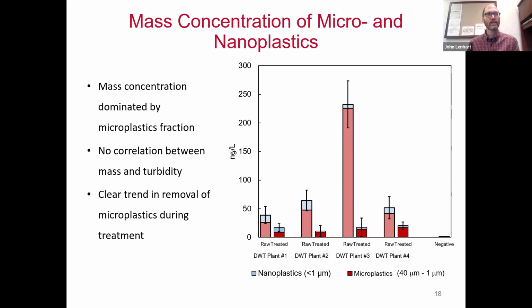And so it's important to note that those particle concentrations, 100,000 particles or whatever, are related to a mass concentration that's in the nanograms per liter. So we're talking small masses of particles. Even though it seems like there's thousands of them, the actual mass is very, very small. When we look at the mass, we can see quite a bit of difference in the mass concentrations within these different samples. And this particular sample from drinking water plant 3 had a significant amount of microplastics at the time when we were collecting these samples.